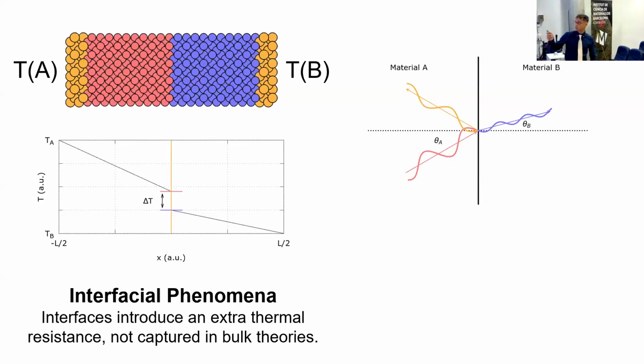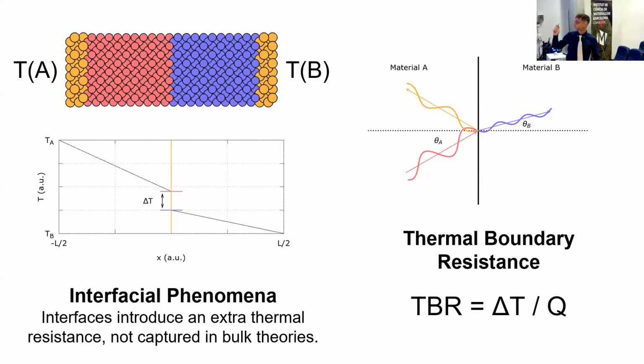This is largely due to the fact that some phonons, when they reach the interface, when they were traveling from left to right, scatter on the interface. So the temperature on the two sides of the interface is appreciably different, especially at the nanoscale. The most straightforward way of characterizing this phenomenon is by introducing the so-called thermal boundary resistance, which is given by the ratio between the temperature drop at the interface and the heat flux, the steady-state heat flux across the material.